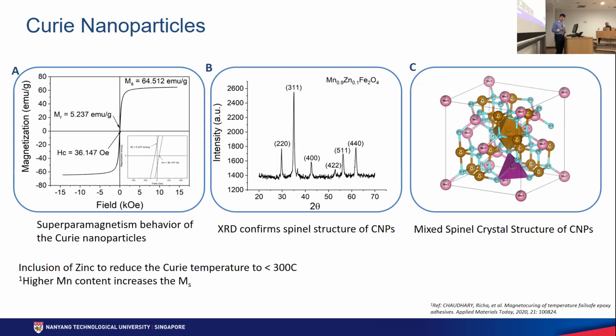Okay, so now we will move on to the magnetic nanoparticles. We call them Curie nanoparticles. Why? Because we don't want it to operate over a specific Curie temperature, in which case is around 300 degrees Celsius. This is the threshold temperature because we don't want any scorching of the organic coating layers or the resin. So that's why, even though higher content of manganese in these nanoparticles increase the saturation magnetization, which give us better